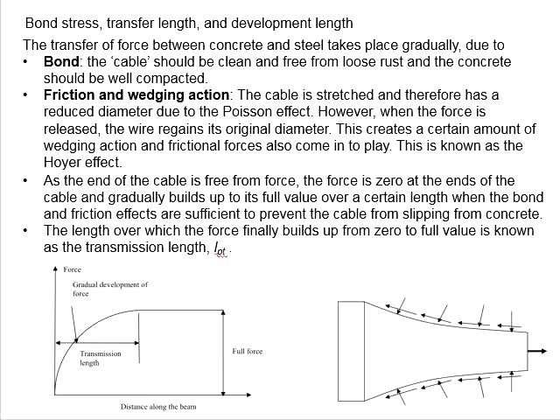When the tendon is stretched, its diameter reduces due to the Poisson effect. When the jacking force is released so stress can transfer to the member, the tendon regains its original diameter. This creates wedging actions and frictional force.